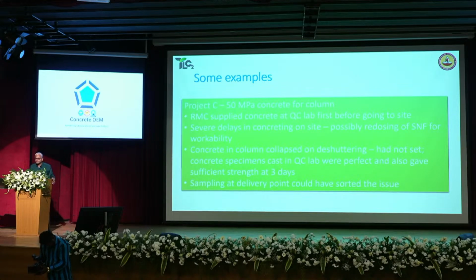The entire column collapsed. There was absolutely no setting in the concrete. And actually, on the third day, when I went to the site, the concrete still smelt of sulfonated naphthalene formaldehyde. I could smell that admixture, that it was overdosed so much. And then I went to the lab and I saw the cubes that they had cast from the same batch of concrete. The cubes were perfect. We tested the cubes, they gave perfect 3-day strength.